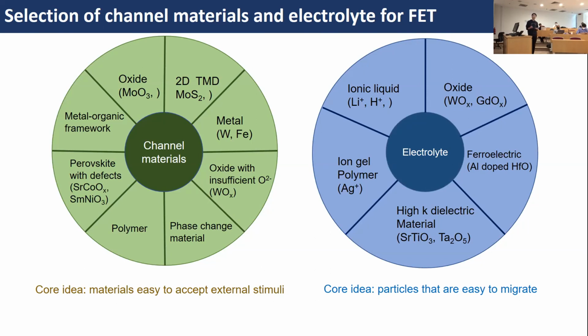Usually, people will choose channel materials such as oxides, 2D materials, metals, or oxides with some oxygen deficiency, for example defects. And for the electrolytes, there are lots of options, maybe ionic liquids, oxides, or some ion gel. The central point here is that we want channel materials that can accept some particles inside. The materials can be porous, or easily oxidized, or the property of the thin film can be changed. Also the change should be reversible, so that we can tune it to some state and bring it back to the initial state.